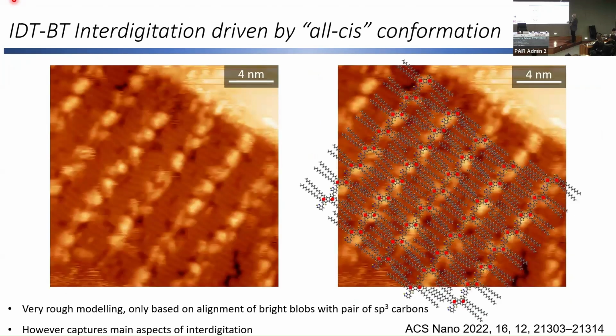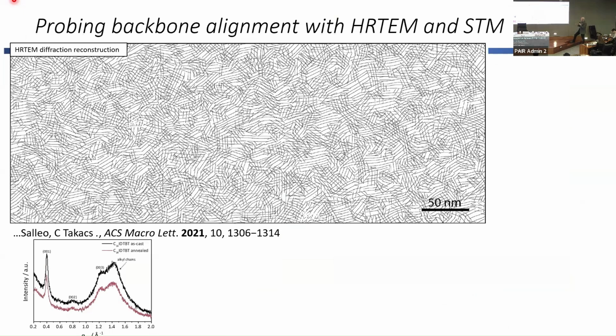And this is absolutely key, because when you look at IDTBT at a lot higher resolution, we do see a lot of short length scale interdigitation. So here's the backbone, and you can see the side chains here, hopefully. And you see this nice spacing here with the side chain density. So when you overlay this structure, you can see now that we have a very realistic representation of the backbone and also the side chains. It matches up, replicates perfectly. And you can see this happens when we put an all-cis conformation on the polymer. All right, I'm going to have to go through much faster.